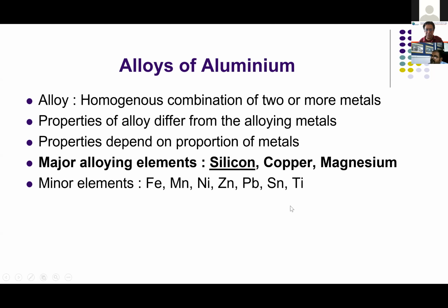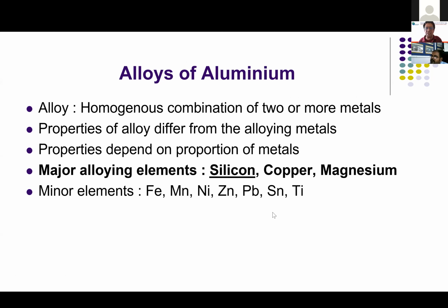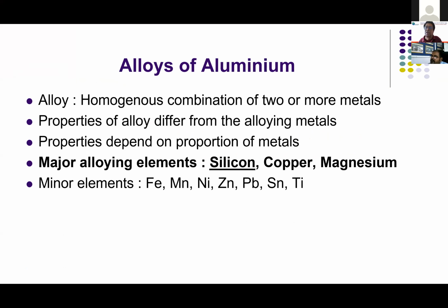Now tin has got a very bad effect. The tin combined with high iron content, let's say 0.8% to 1% iron, the casting becomes very brittle. In pressure die casting, this was one of my personal experiences. For some reason, the tin content went up. The casting became very brittle. While ejecting, castings were cracking. It was very difficult to remove from the die. They kept on adjusting the die, polishing the dies and everything. Castings still were cracking. And while handling it and while fettling it, we were losing more castings. Then later we found out it was tin which was the culprit with the high iron. 1.1% iron and a little bit of tin was present.